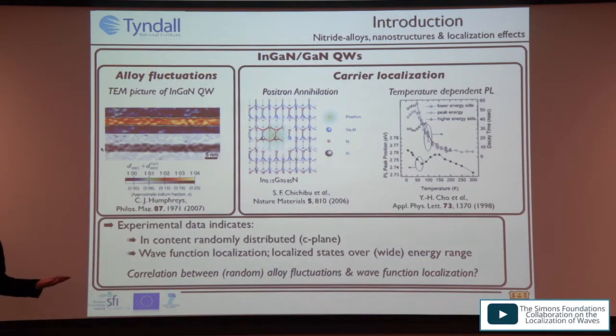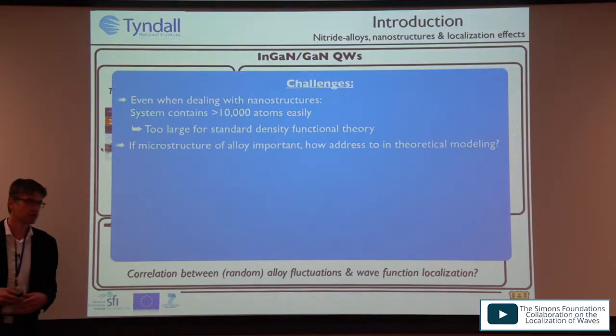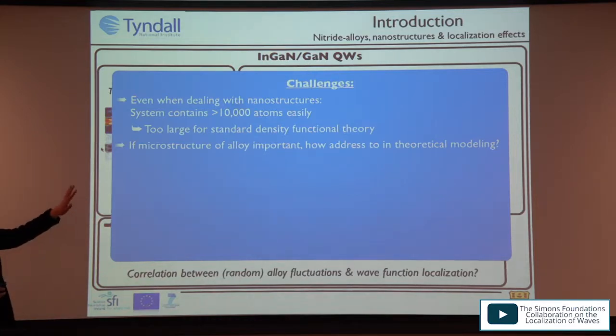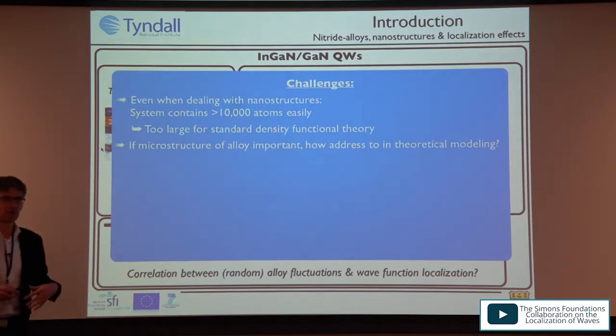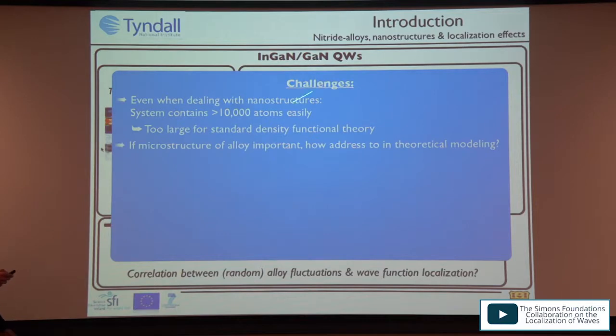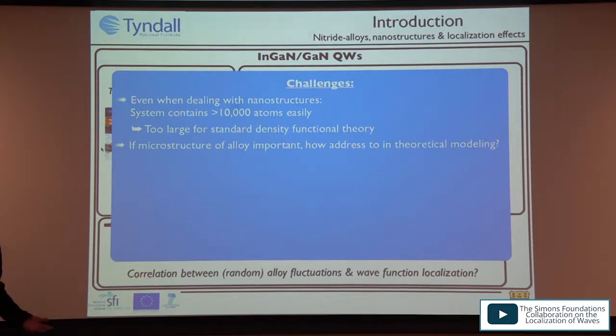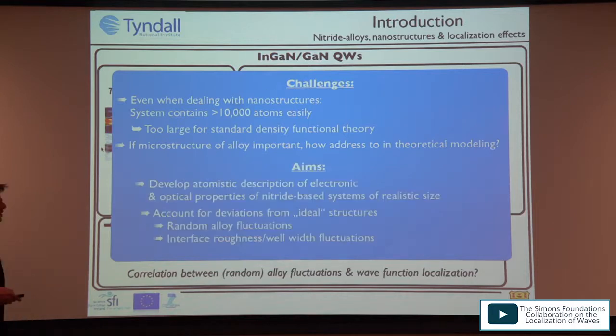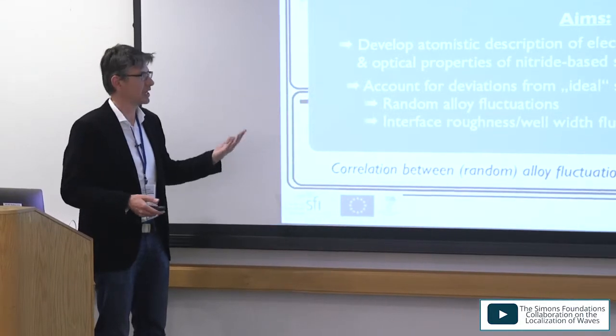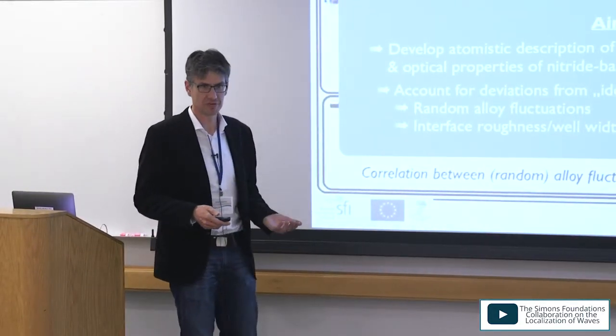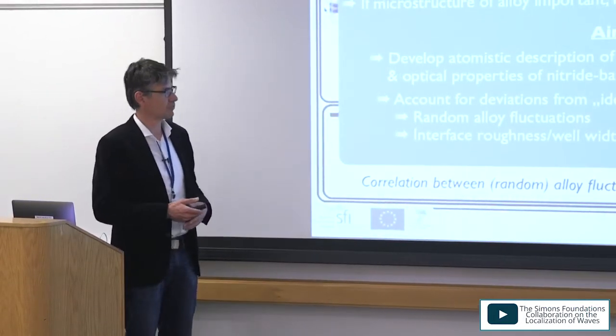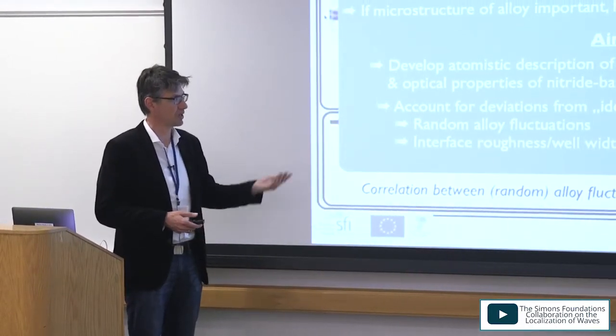However, thinking in terms of an atomistic description, this is not straightforward. When dealing with a nanostructure we must treat not only the active region but also the barrier material, and with alloy fluctuations and in-plane dimensions, we need around 10,000 atoms. Standard DFT — not linear scaling or orbital-free DFT — is out of reach for this. Our aim was therefore to develop an empirical atomistic description of the electronic and optical properties of nitride-based systems of realistic size, allowing treatment of tens of thousands of atoms while accounting for alloy fluctuations, interface roughness, and well-width fluctuations.